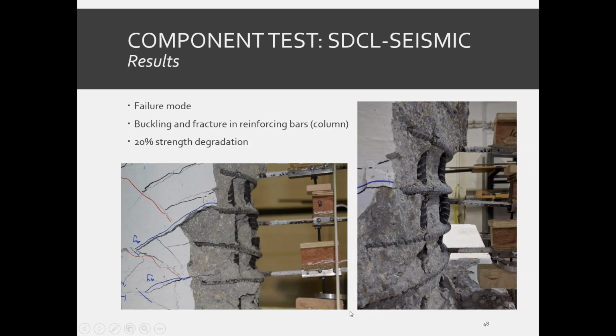The mode of failure for the experiment was fracture and buckling of rebars. At this stage, we observed that the core concrete of the column had crushed extensively. From the hysteretic curve, we found that almost 20% strength degradation had occurred, and at the end of the first cycle of the 7 delta Y displacement level, the testing was halted.